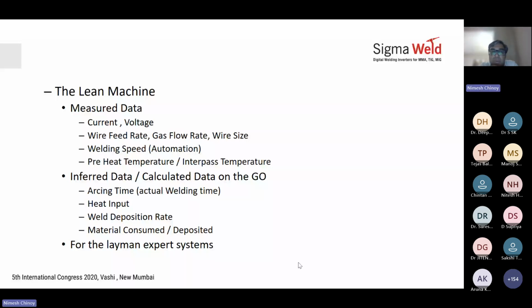And this can help you calculate the heat input. And if preheating was mandatory, what is the preheating temperature and interpass temperature? If the material is sensitive, they will ask that the interpass temperature must be maintained between 120 to 150 degrees. Then you can measure the temperature, and if it goes beyond that, you can give an alarm saying the temperature is too high, don't allow to weld.